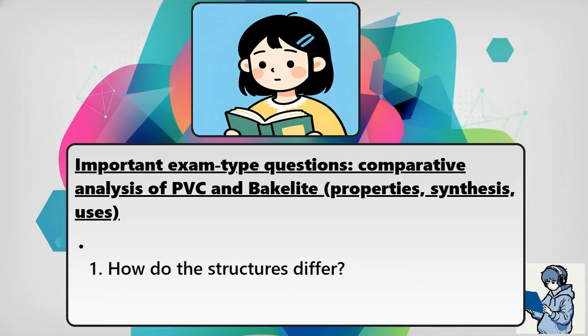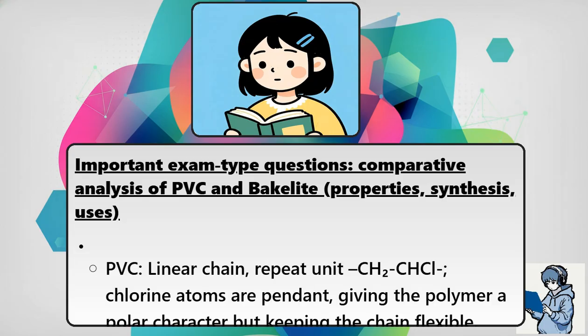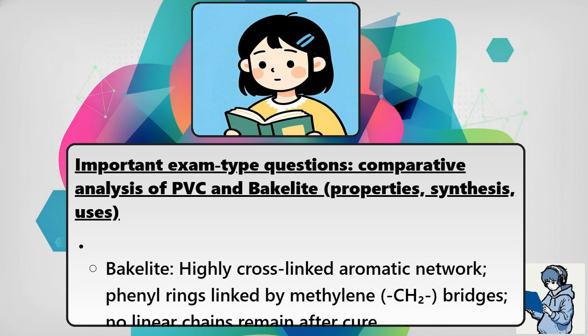2. How do the structures differ? PVC: linear chain, repeat unit CH2CHCl. Chlorine atoms are pendant, giving the polymer a polar character but keeping the chain flexible. Bakelite: highly cross-linked aromatic network. Phenyl rings linked by methylene CH2 bridges. No linear chains remain after cure.